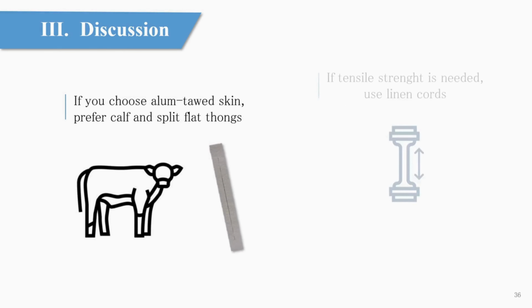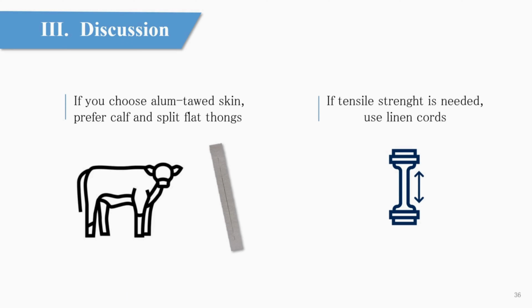Regarding sewing supports, calf skin seems more suitable than goat skin for this purpose, as suggested by Christopher Clarkson in the literature. It's indeed more rigid. Similarly, flat thongs, because they are stiffer, seem more suitable than twisted thongs. The low extensibility of the sewing supports avoids creating a concave spine when the book is closed. Linen cords are really resistant to traction, which can be an advantage when the binding has heavy boards, for example.